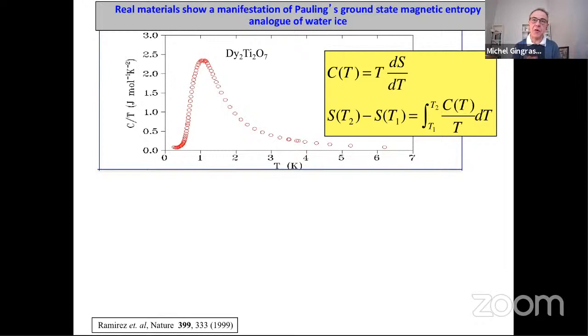What these folks did is they followed the same thing that William Giauque had done for water ice. They measured here the magnetic specific heat for dysprosium titanate, one of these two materials which are candidates for spin ice. At these low temperatures, that's the nice part of this problem, one doesn't have to worry about phonons. The phonons are frozen out. And so one can measure the specific heat. And through this thermodynamic relationship here, by measuring the specific heat between two temperatures, T1 and T2, one can integrate C over T and calculate the entropy S that got removed between these two reference temperatures.